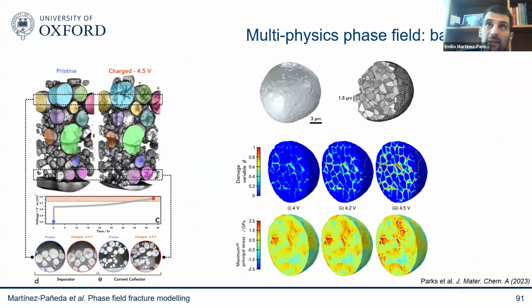And not only can we go up the scales, we can also go down the scales. So these people, again, are very good at imaging. So they can image in XCT scans particle cracking at the micro scale. So we can embed those particles with multiple cracks, and we can understand a lot of these particles crack at the grain boundaries. So we can understand when things will fail at the macro scale level.